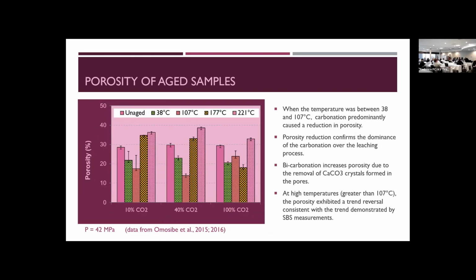We also measured the porosity of the samples, and we noticed some changes in porosity. This time, looking first at 10% CO2, you can notice that at 107C we observed the lowest porosity change, whereas at higher temperature, especially 221C, we observe the highest porosity in the cement compared to the others. And this porosity trend was similar at 40%, but totally reversed at 100%